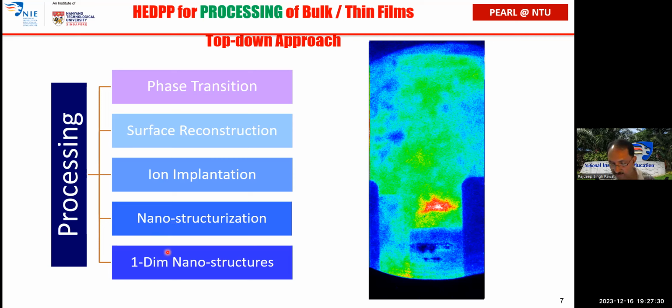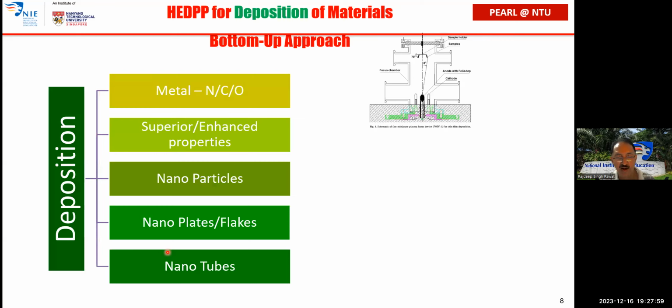We have also converted thin films into nanostructures, not necessarily on a solid target: you deposit the thin films, expose them to the plasma focus, and we have formed very nice nanoparticles with a very uniform size distribution for our FePt and CoPt work, because we did dedicated work on magnetic materials. We have also grown one-dimensional nanostructures on polyaniline thin film. All these works are well published.